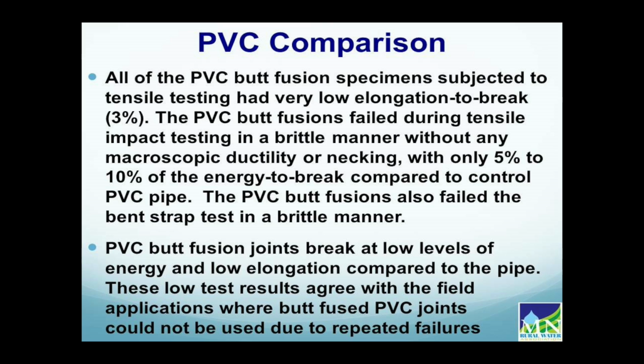In the case of PVC, all of the PVC butt fusion specimens subjected to tensile testing had very low elongation to break, about 3% of the control pipe. In the tensile impact test, our testing showed about 5 to 10% of the energy to break compared to the control pipe, which agreed well with the other laboratory's high-speed tensile impact value of about 9%. The PVC butt fusion joints break at low levels of energy and low elongation, and I believe that's because however these were made, there simply wasn't enough ductility to the butt fusions. These low laboratory values agree well with the field applications where there have been a number of butt fusion failures.